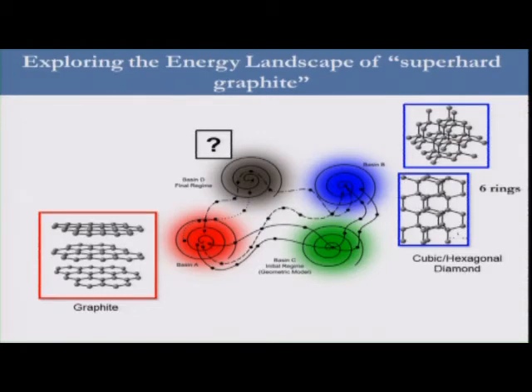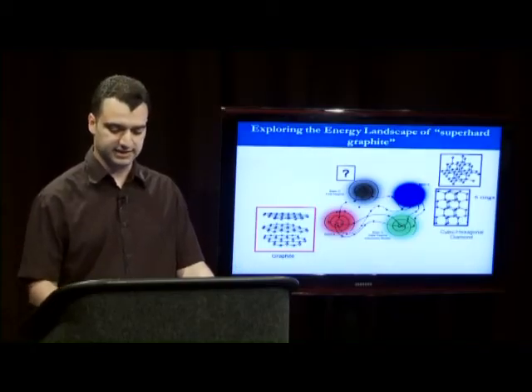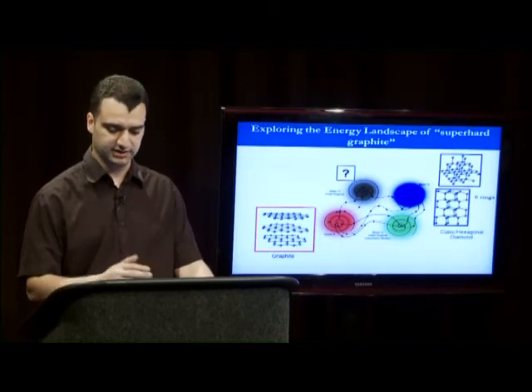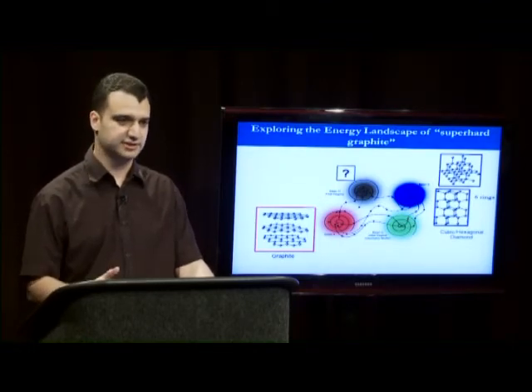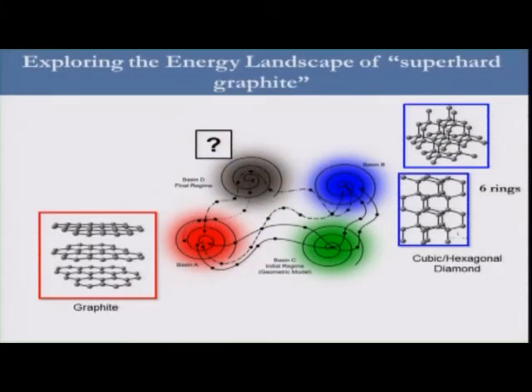So we will use the following procedure: instead of starting from A to a known B, we start from a less likely or less probable path beginning from graphite. We take the path from graphite to cubic or hexagonal diamond, knowing that this transition takes place at high temperature. If we perform our simulation at ambient temperature — 300 Kelvin — we are not only going to optimize the transition route, but also the endpoint, because diamond in its cubic or hexagonal form is less likely to form at 300 Kelvin.